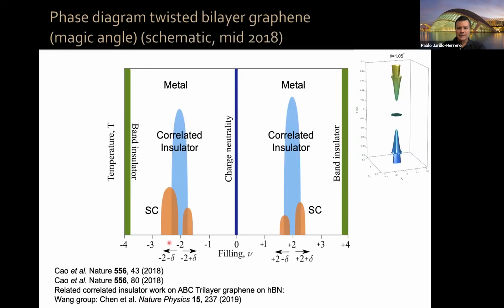Now, if we go to magic angle graphene, this is the phase diagram, temperature again versus filling factor. You have charge neutrality, you have band insulators when your chemical potential is in these band gaps. Here is a flat band, this is for 1.05 degrees. And now, as you fill these flat bands, you can see regions near -2 and +2, okay? You have correlated insulator behavior, as I showed yesterday. And then if you dope away from it, you have superconducting domes. Whether you see all 4 of these domes or only 2 or only 1 depends on details, okay?